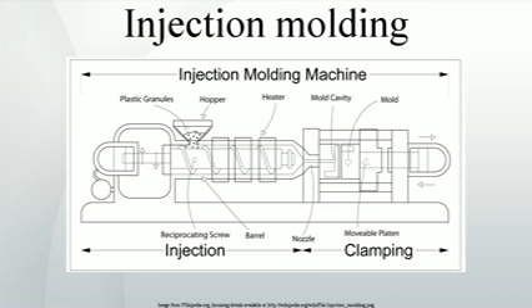If the skin is too thin, then the molded part will tend to shrink onto the cores that form it while cooling and cling to those cores, or the part may warp, twist, blister or crack when the cavity is pulled away. A mold is usually designed so that the molded part reliably remains on the ejector, B, side of the mold when it opens, and draws the runner and the sprue out of the A side along with the parts. The part then falls freely when ejected from the B side.